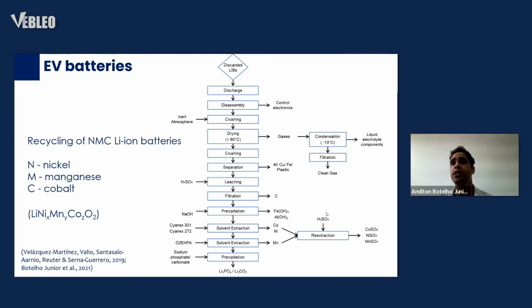And then a precipitation to remove iron and aluminum. Solvent extraction is a liquid separation using an organic phase to obtain cobalt, nickel, and manganese. And finally, lithium is obtained by precipitation as phosphate or carbonate. And then it's possible to obtain cobalt, nickel, and manganese sulfate separated or together.